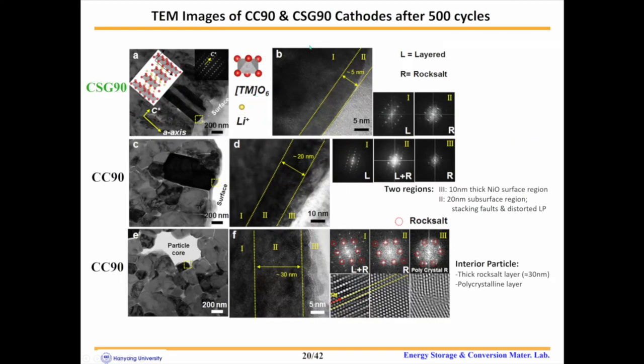This is a TEM image of the two cathodes after 500 cycles. The CSG90 cathode particle exhibited a thin nickel oxide-like impurity layer of five nanometers on the particle surface. On the other hand, surface damage of the CC90 is more severe than that of the CSG cathode because of the nickel-rich outer surface, showing an impurity layer of 30 nanometers. In addition to surface damage, the interior primary particles also suffer from severe damage due to electrolyte attack through the formed micro cracks.